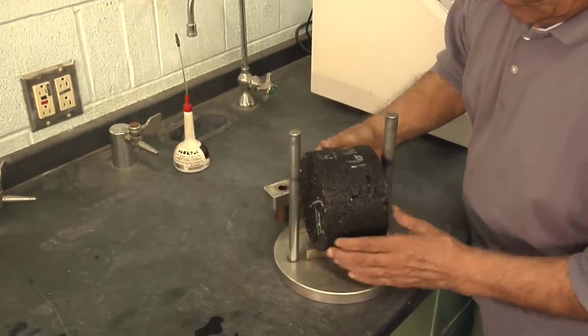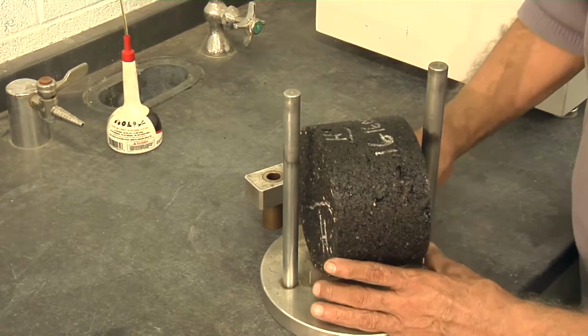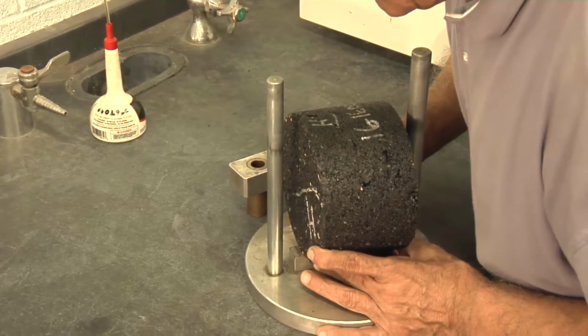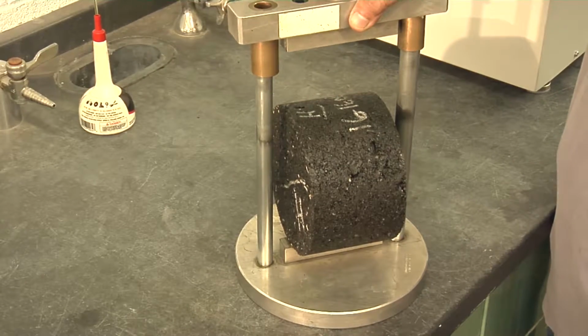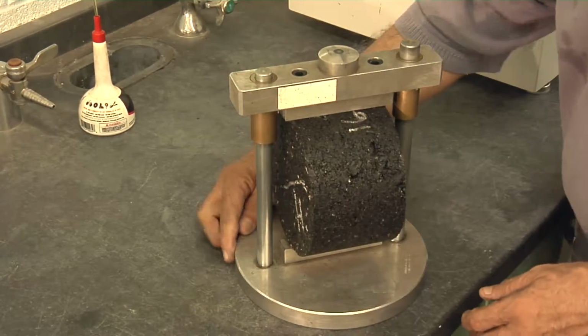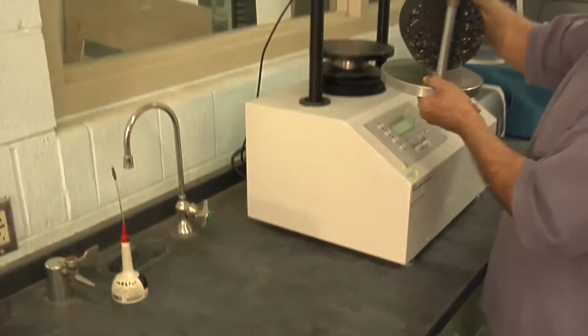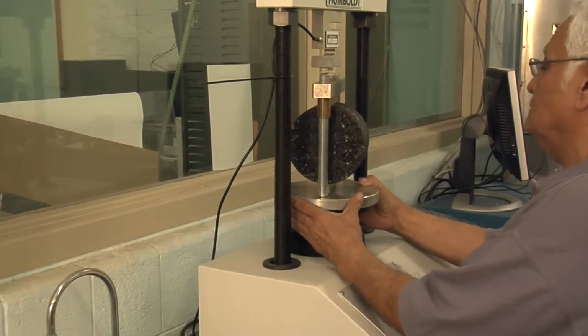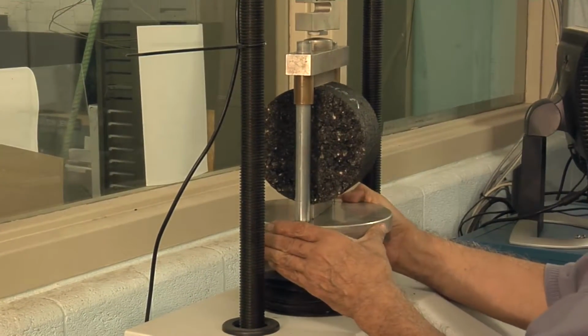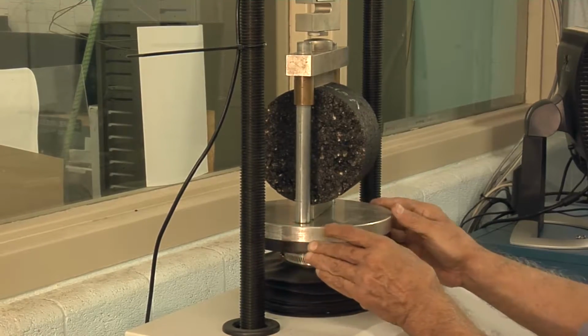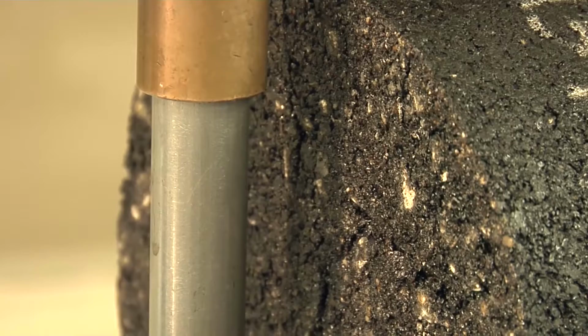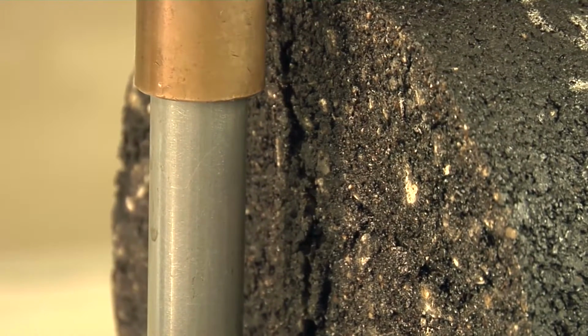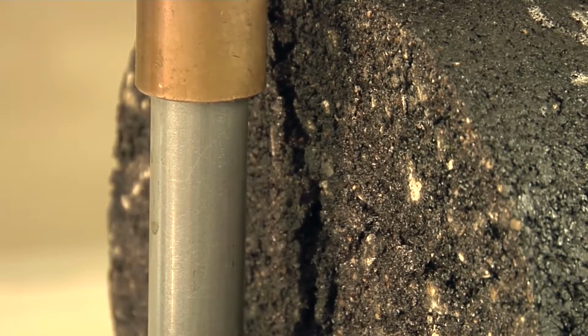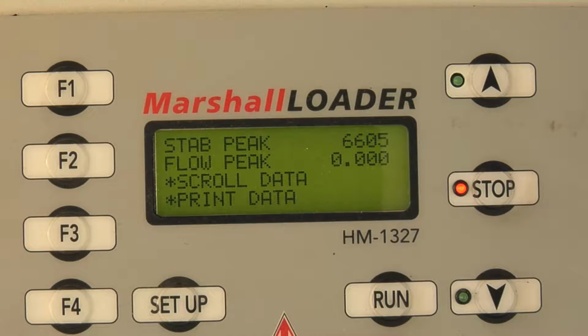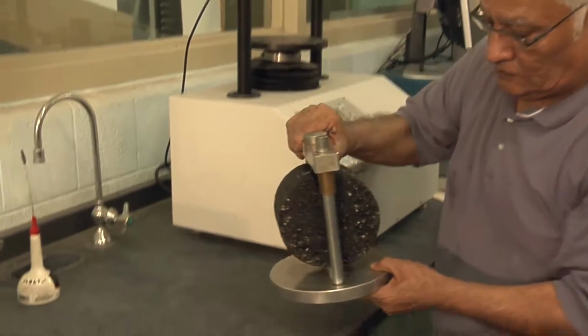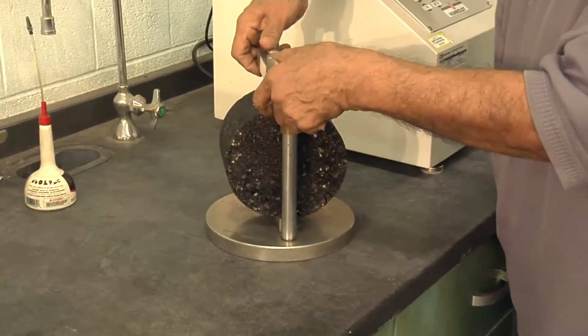Proceed to test samples in the load frame with the split tension device installed. Be careful to seat the sample properly into the split tension device before testing the sample. Run the machine until the maximum load has been achieved and record the results. After recording the maximum compressive strength, remove the specimen from the split tension device and pull apart. Record and inspect for stripping or broken aggregates.